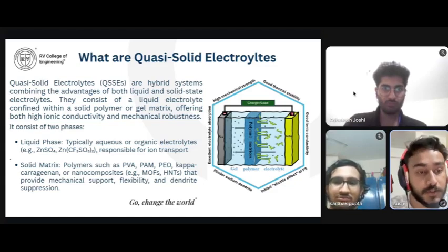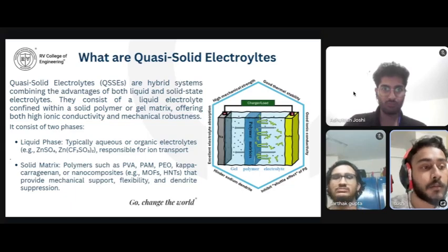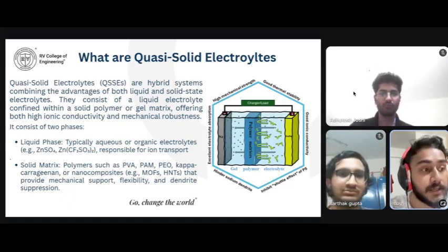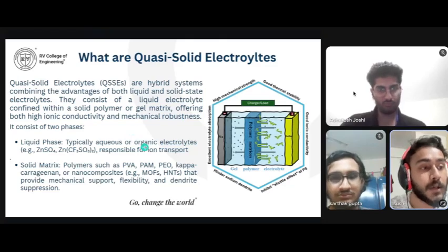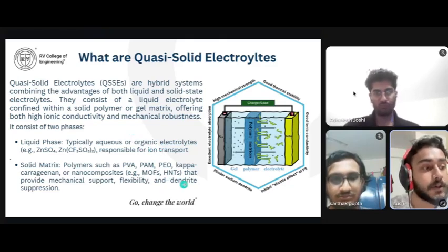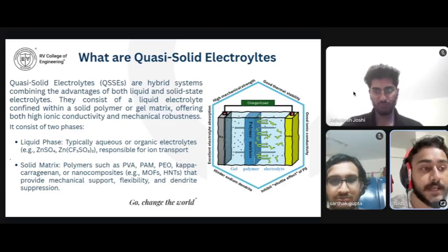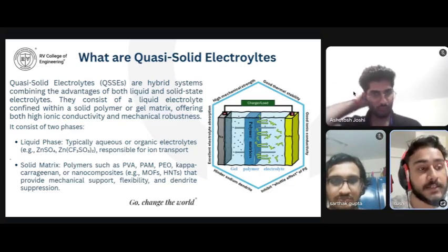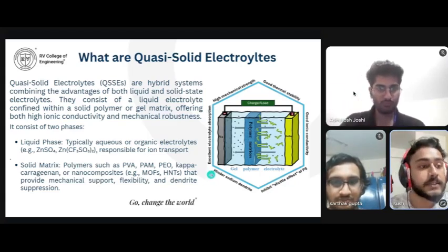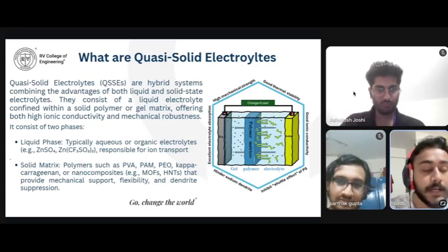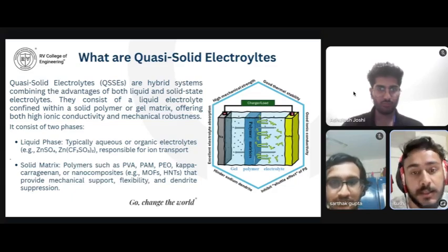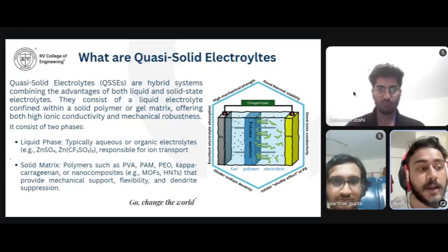These handle ion transport. The second component is the solid matrix, which is made from polymers like polyvinyl alcohol, polyacrylamide, or polyethylene oxide, or nanocomposites like MOFs, which stands for metal-organic frameworks, or halloysite nanotubes, which provide structure, flexibility, and dendrite suppression. On the right, we can see an image. In this, a liquid electrolyte is trapped within a gel or polymer. This structure ensures both ion movement and structural integrity, making it ideal for flexible, high-performance batteries. Next slide.